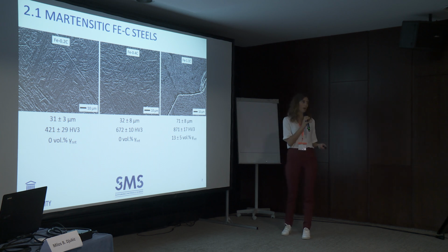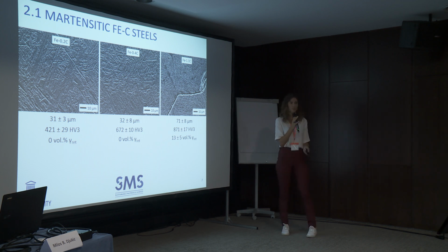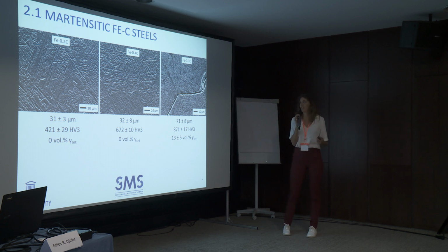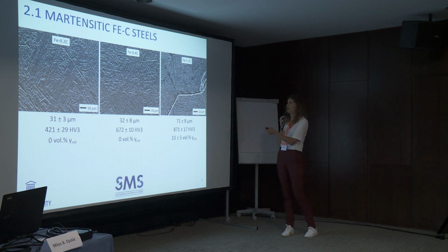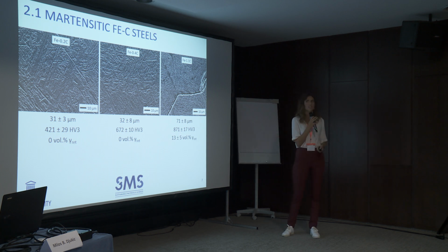This is because it has a very high critical cooling rate, and thus it had to be heat treated at higher temperatures to obtain a fully martensitic structure upon quenching. I say fully martensitic, which is in fact not entirely true, because it also has a high amount of retained austenite. The hardness increases with increasing carbon content due to carbon in solid solution, which is generally accepted. The high amount of retained austenite is something special in this 1.1 carbon steel, but we also have a high amount of quench cracks due to its very brittle character. The interaction between retained austenite and quench cracks with hydrogen is studied in depth in this study.